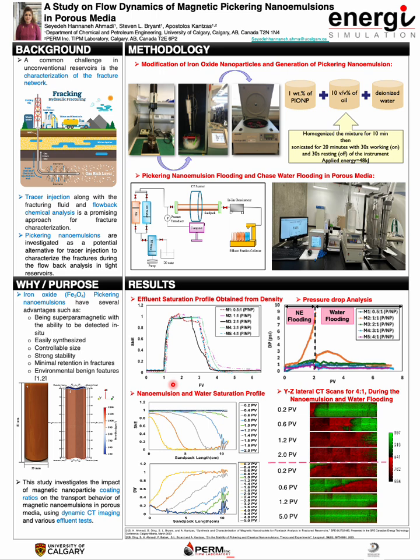Continuous injection of the nanoemulsion led to complete saturation of the sandpack with nanoemulsion, as the line is equal to 1, as evidenced by the effluent saturation profile matching the nanoemulsion saturation baseline. During the chase water flooding, the saturation profile gradually decreased, ultimately approaching the initial water saturation. However, the saturation profile didn't align with the water saturation line, indicating the presence of oil droplets in the effluent throughout the experiment. This trend was consistent across all experiments, indicating that the nanoemulsion was progressively displaced from the sandpack.